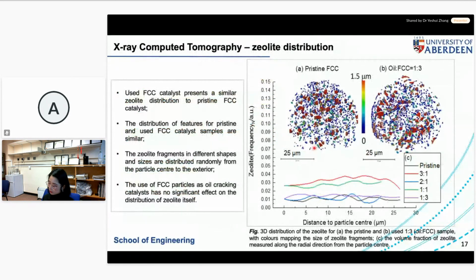Except for these different contributions of the composition, we can also segment the size distributions for one type of component. For example, the zeolite, because it provides the acidity of this FCC catalyst to catalyze the process. That's why we want to find out more information about this zeolite distribution. If you look at these color maps, the different colors represent the different sizes of these zeolite fragments throughout this single FCC catalyst particle.